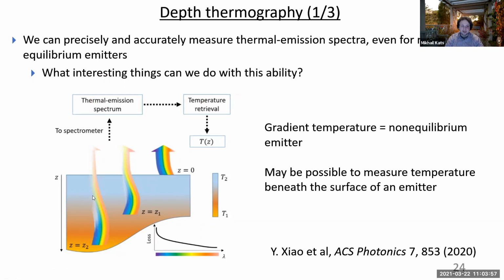And by the time it gets up here, some of the light got absorbed, but of course, a different amount of light got absorbed at different wavelengths. And so you should be able to use that information to invert the thermal radiation spectrum into the temperature as a function of position. And so this is what we tried to do.